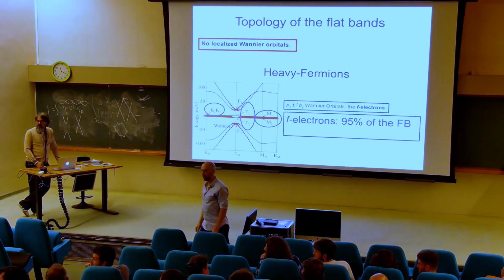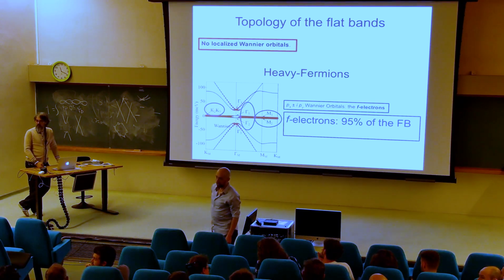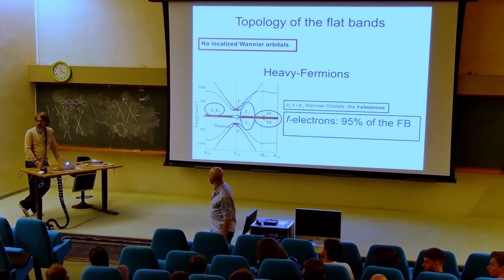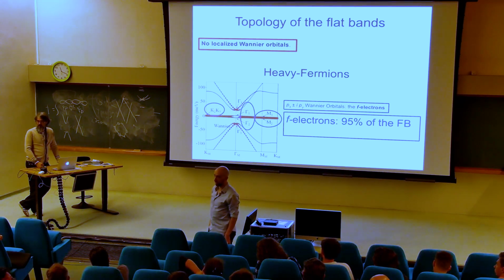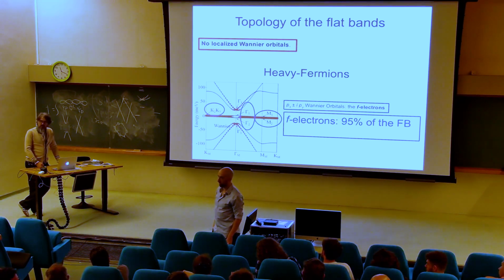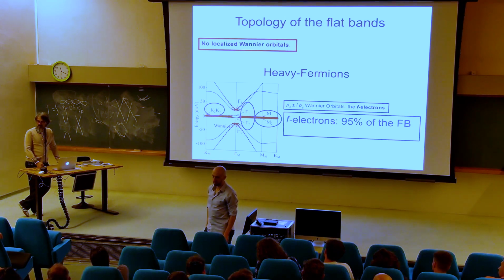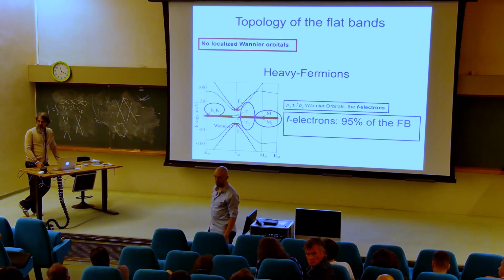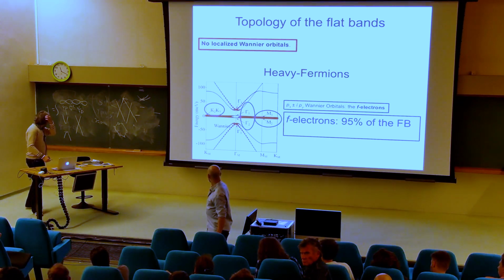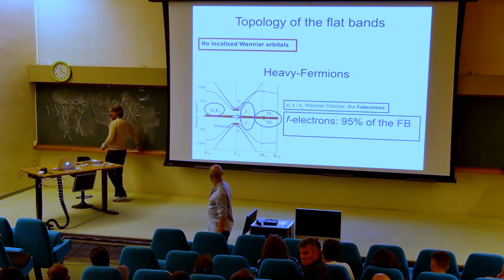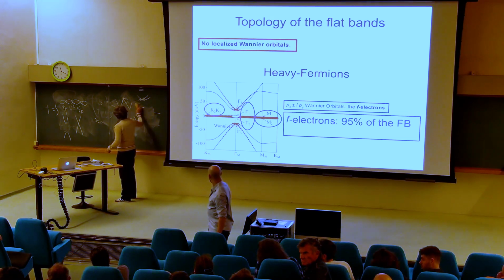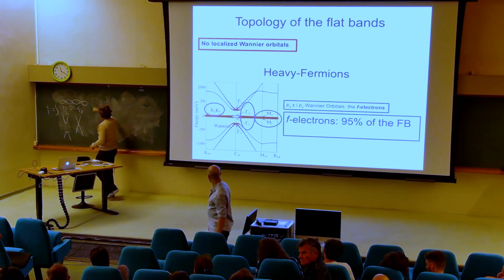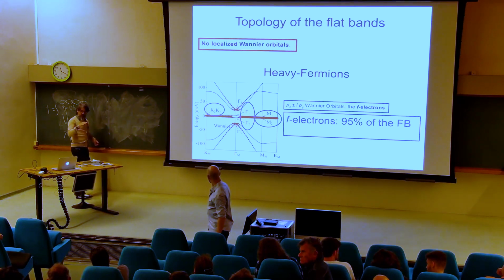Concerning the degeneracies at gamma and at K, especially at K, if you have an electric field that is perpendicular to your bilayer, you keep the order 6 or the order 3 rotation, but you lose all the order 2 rotation along the plane, and in some cases, and not some other ones, you no longer have degeneracies at K. I think with an electric field that's perpendicular. Without electric field, it's always degenerate, I agree.